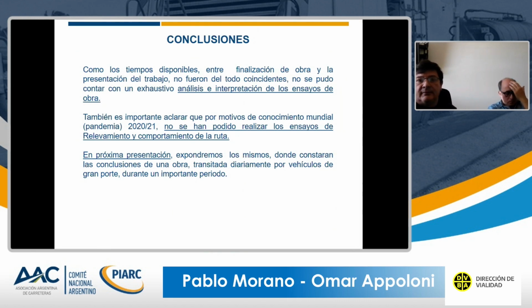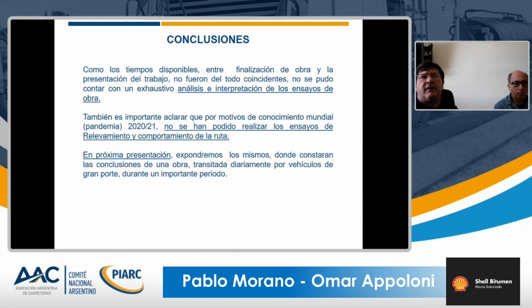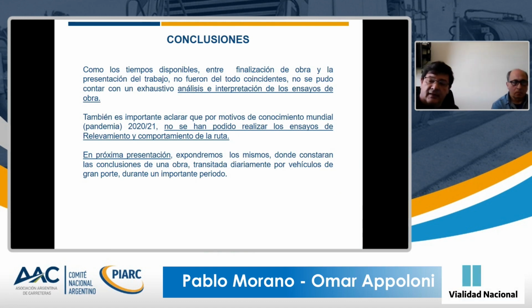The conclusions. Here what's important is that thanks to the experimental and lab stages, we were able to apply this to actual works on roads in the province of Buenos Aires, and we are planning 2 more. And really, the important thing here is to notice the good behavior of this type of base and the reduction of asphalt thickness.